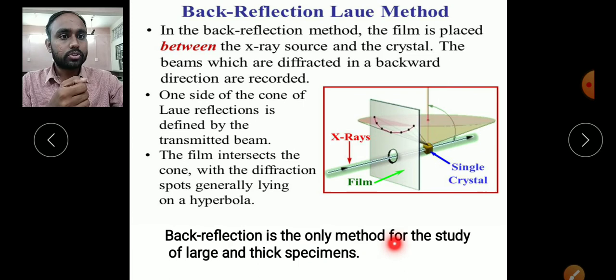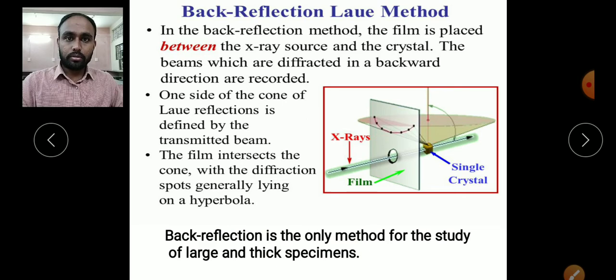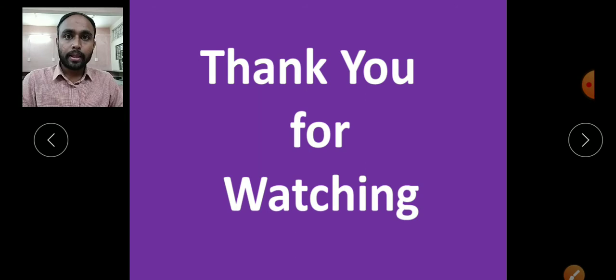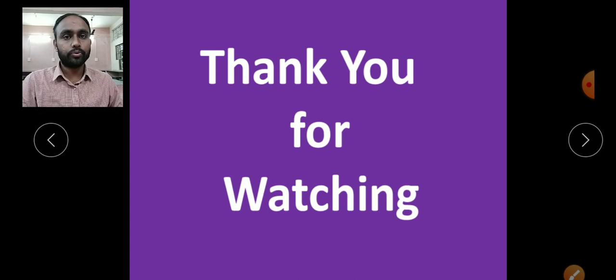The back reflection method is the only method suitable for the study of large and thick specimens. If we have a thick crystal specimen, we should use the back reflection Laue method instead of the transmission method. Both methods are very useful for determining the symmetry of the crystal, but more specifically the back reflection method is used for thick and larger specimens.